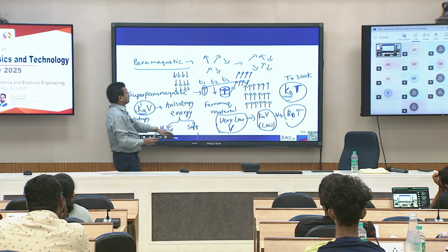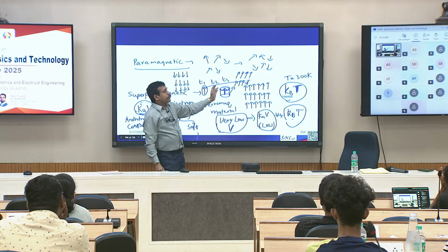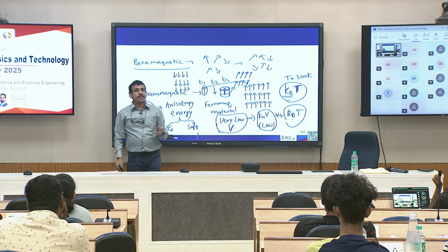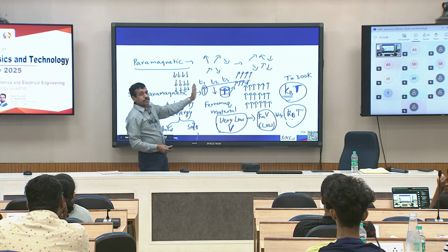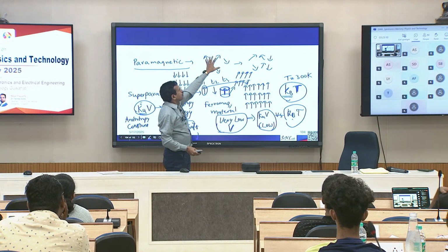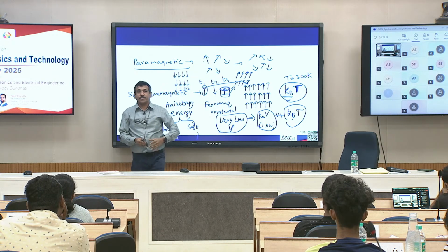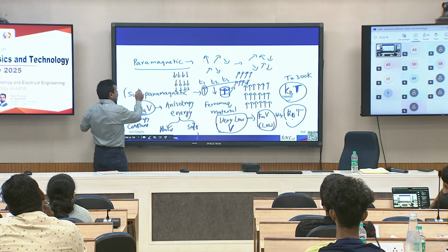So, your particle is still ferromagnetic, but the particle magnetization is fluctuating. Okay, particle magnetization is fluctuating as a function of time, like the atomic magnetic moments fluctuate in a paramagnetic material. Okay. So, that phenomenon is called super paramagnetism.